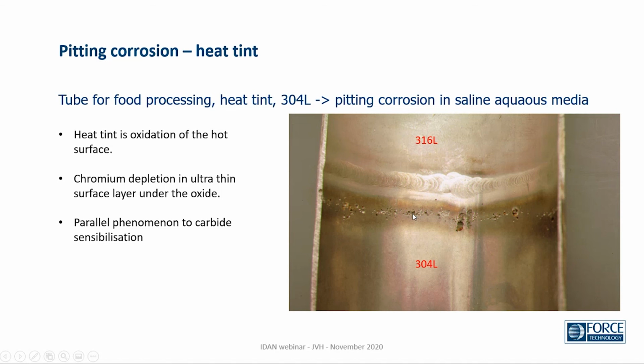In fact, this phenomena is the same as we saw with the carbides. We have a depletion, lower level of chromium, but not around carbides. Here it's below an oxide layer on the surface. The oxide is rich in chromium, and when it's formed, it drags chromium out of the material into the oxide, and you have a very, very thin layer. We're talking about μmeters below, which is sensitive. But once a crevice or a pit has formed, it will grow, even though it gets into sound material below this depleted layer.